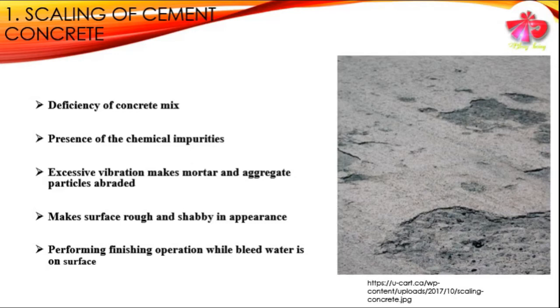The first typical failure pattern is the scaling of cement concrete. Scaling is mainly due to the deficiency in the mix or the presence of chemical impurities. Excessive vibration given to the mix during construction causes the cement mortar to come to the top, which gets abraded, exposing the aggregates of the mix and making the surface rough and uneven in appearance.